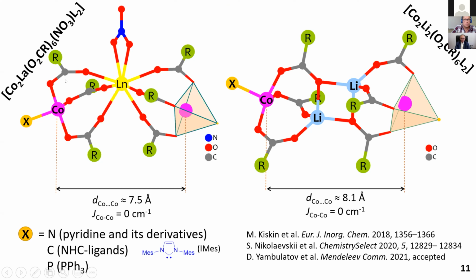Carboxylate groups don't create significant steric hindrance, so we can use bulky ligands, and the exchange interaction between cobalt atoms is zero due to the long distance between them, more than 7.5 angstrom. And the choice of ligand: it's a nitrogen-containing ligand, pyridine derivative, triphenylphosphine, and carbene ligands.